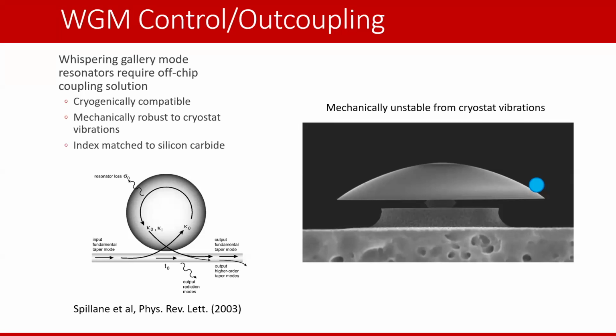And we tried this, and in the cryostat, the mechanical vibrations from the cryostat that are required to keep the defects down at 4K, to keep their spin coherence, cause so much vibration that the tapered optical fiber acts like a giant guitar string and will not sit and controllably couple to our whispering gallery resonators. And so this makes running experiments extraordinarily difficult. In addition, the index of the optical fiber means that this is undercoupled to the cavity mode, and you can't ever actually overcouple. Part of what would be nice is if we could control the coupling to the cavity mode, because this allows us to interrogate the system in different regimes.